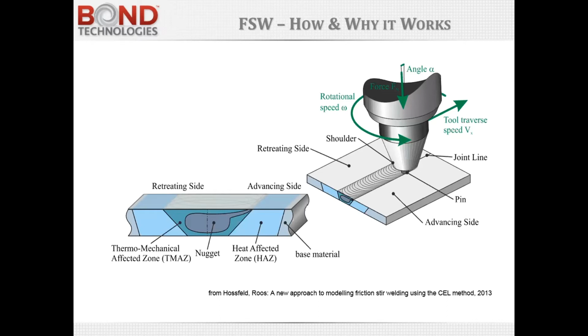To the right, we're showing some of the key parameters that are involved in the process. The forge force is pushing down on the joint as it stirs. There's a rotational speed, there's a traverse speed. So speeds and feeds, much like metal cutting. The tool has a pin and a shoulder. And there's an advancing side and a retreating side, which is notable. So if you jump back to the picture on the lower left, you'll see a little bit of a tail on the advancing side. So it is not a perfectly symmetrical weld nugget.